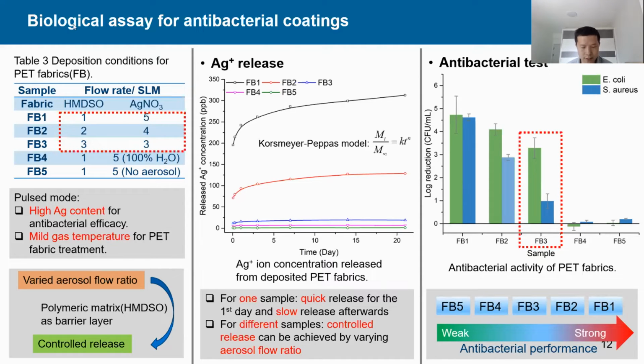The antibacterial effects of silver embedded coatings directly depend on the release of silver ions. We measure the release with ICP-MS. A higher amount of silver release is found on sample FB1, as we see in the figure, due to the larger flow ratio of silver nitrate aerosols and the thinner barrier layers against the release, which is formed by HMDSO. It's necessary to mention that there's a 2-phase release kinetics for all deposited samples.